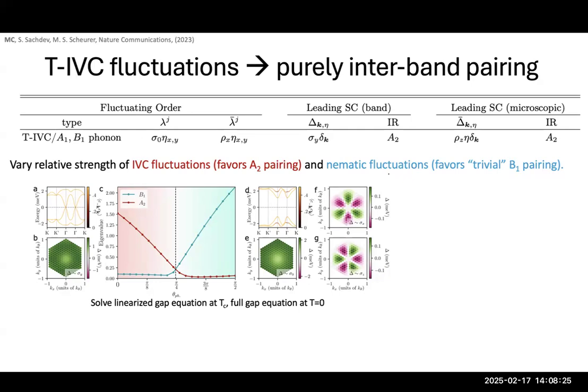So going from here to here, here is where you have IVC fluctuations. This is where you have nematic fluctuations. We find the interband state is favored and then is killed by the nematic fluctuations, which lead to this fully gapped trivial state. And so we find essentially that our commutator criteria predicted the right thing, that when you do the full mean field, you get good agreement. But the more interesting thing, I think, is in the spectrum you get in either case.